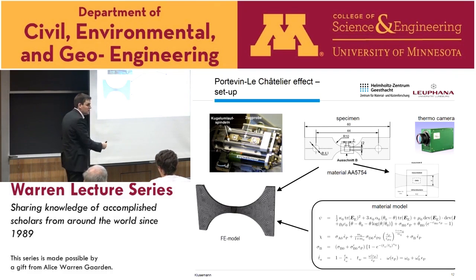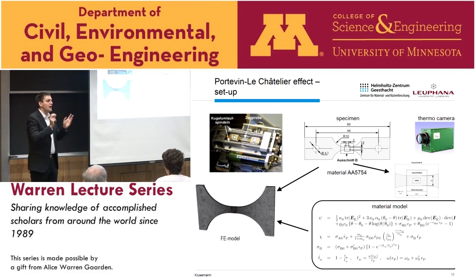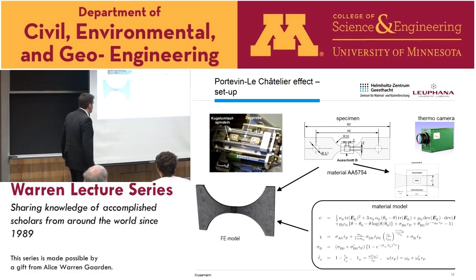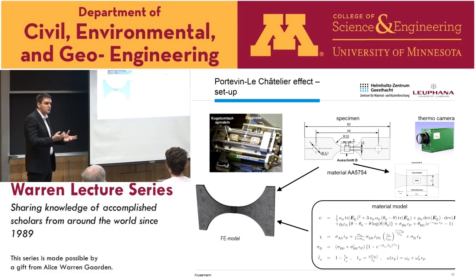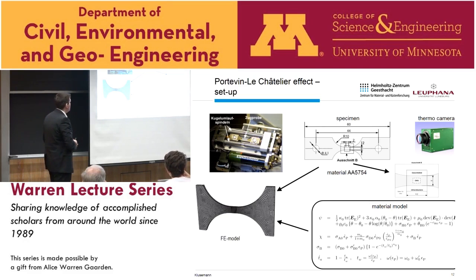So this is in principle the central equation for this PLC effect, where you have this t_a, which is the so-called aging time, which of course depends on a waiting time. In principle, a dislocation has to wait at these solute atoms, which then depends on this function omega, which is again a function of the strain itself. So this was incorporated into Abaqus as a user material. And first of all, we had to identify, of course, some material parameters. This was the first step we had to do.